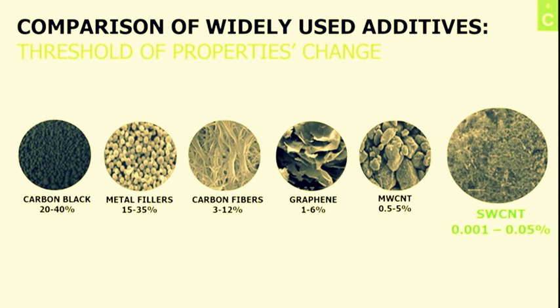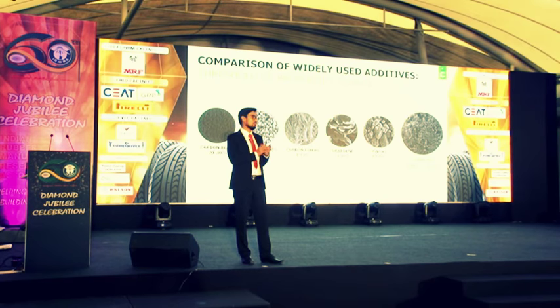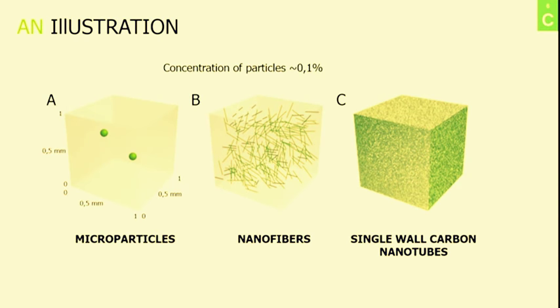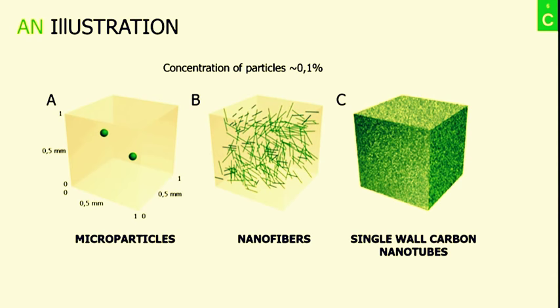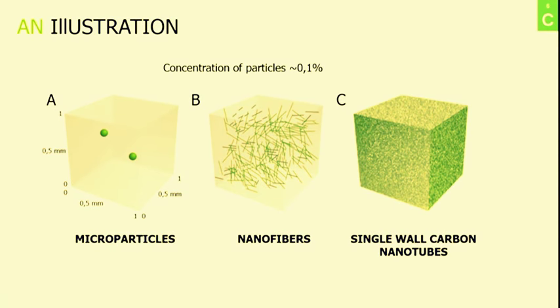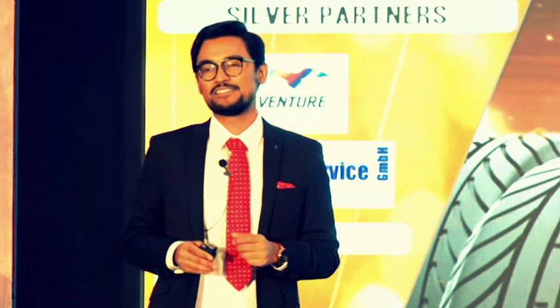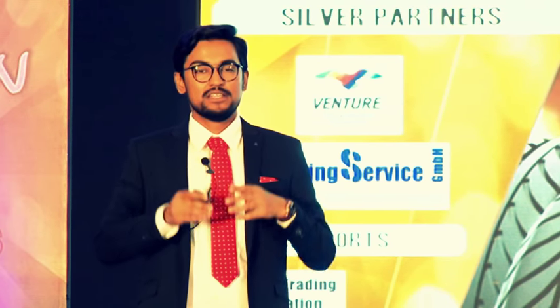If you compare it with other additives, and my ambit is not only rubber, I'm talking about all the polymer additives, you would find that single-wall carbon nanotubes are used in very, very low concentrations. The reason is the very high aspect ratio, length to diameter ratio, and its hollow structure. Because single-wall carbon nanotubes do not have anything inside them, they are hollow. That is the reason why they can be used to bring about a significant change in the properties of the material at very, very low concentration. This is just an illustration where you can see if we put similar weight of microparticle, nanofiber, and single-wall carbon nanotube into a similar volume, single-wall carbon nanotube would give much larger coverage of the area, hence their properties.